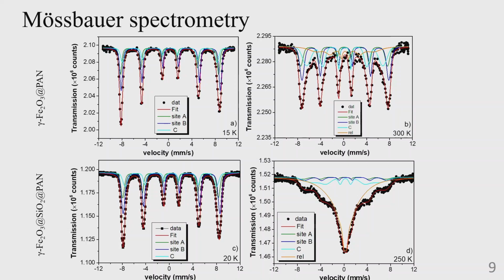For this analysis, we use the well-known sextet patterns for the A and B sites of the iron oxide with the inverse spinel structure. Additionally, for contributions at the higher temperatures, we added a relaxation pattern for both samples, only for the room temperature spectrum here and here. For the first sample, the 300 K spectrum is broadened, expected from the increasing fluctuation dynamics of the magnetic nanoparticles.